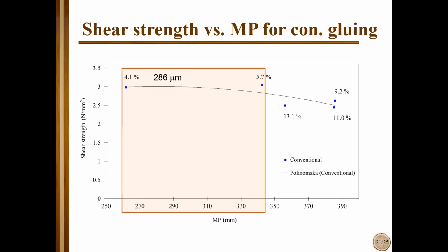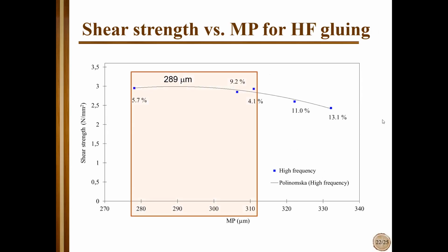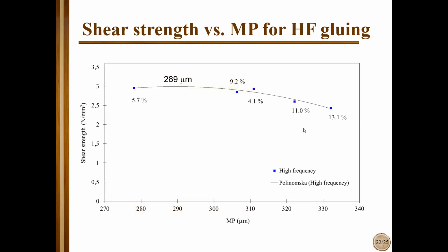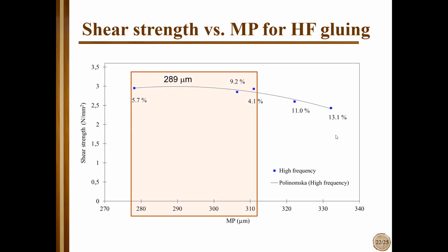In some special cases, we have over penetration, like with thin veneer, where adhesive comes out through the thickness onto the surface. This certainly does not help the shear strength, and additionally has quite a bad look or decorative appearance. Another result was for conventional gluing. This is for high frequency gluing. Almost the same results. Again, we got some kind of maximal shear strength at penetration depth of about 300 micrometers. So if adhesive goes too deep, shear strength starts to decrease.